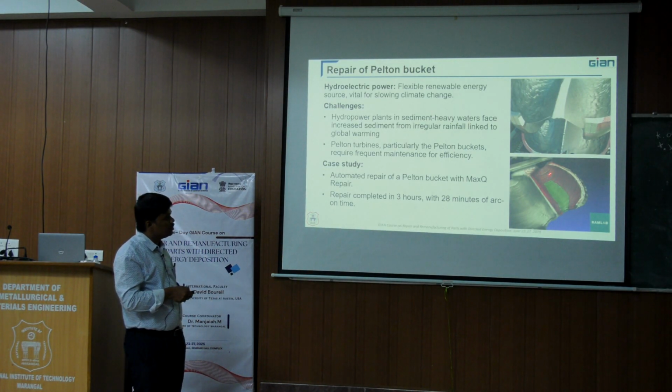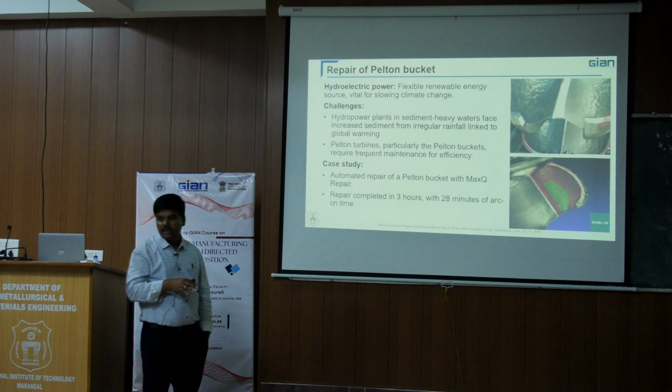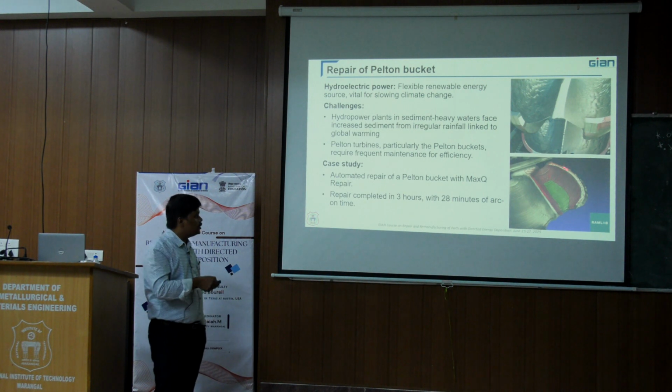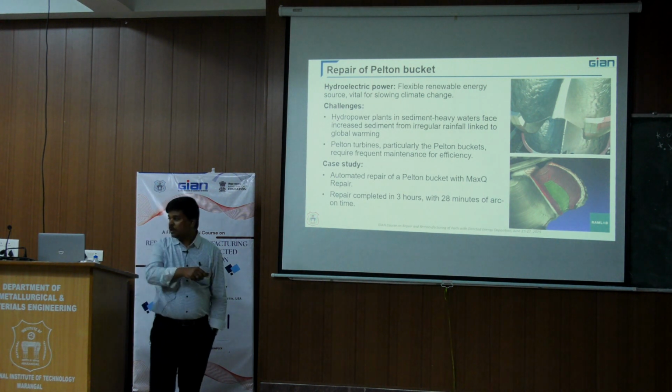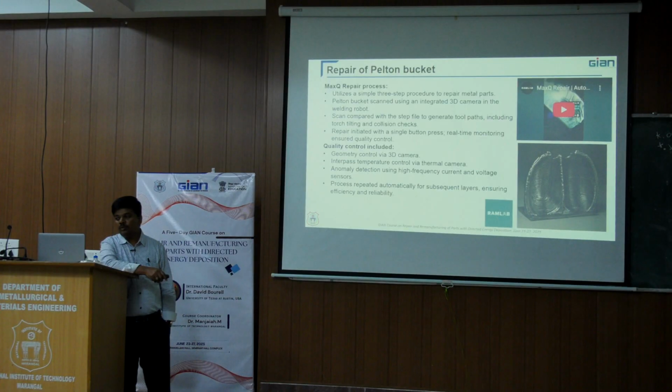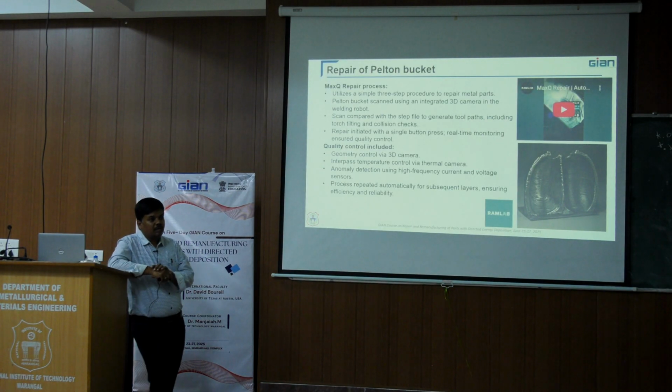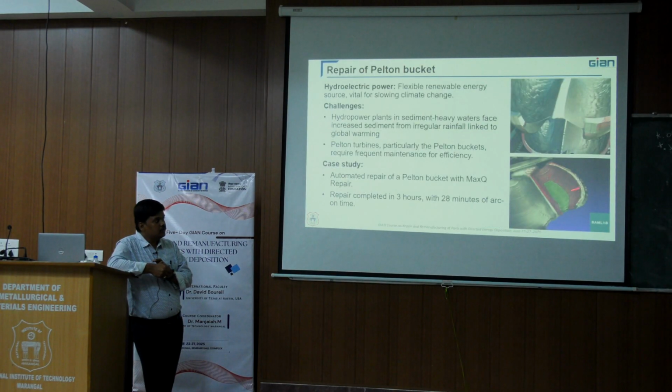This is the worn out area. They have taken this Pelton bucket surface area with 3D scanners, and they have tried to understand how extensively the wear has taken place, what the volume is, and what kind of deposition strategies we have to use for fabrication of repairing of these parts.